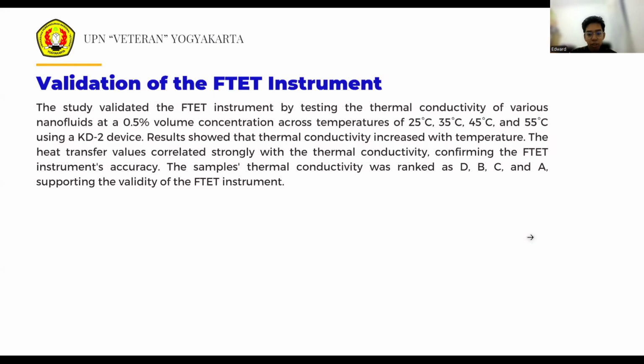To further validate the FTET instrument, the heat transferred by the nanofluid was compared with their thermal conductivity. The study found a strong correlation between the thermal conductivity curves and the heat transfer value, confirming the accuracy of the FTET instrument. The thermal conductivity of samples was ranked in order of D, B, C, and A. This verification supports the validity of the FTET instrument created in the study.